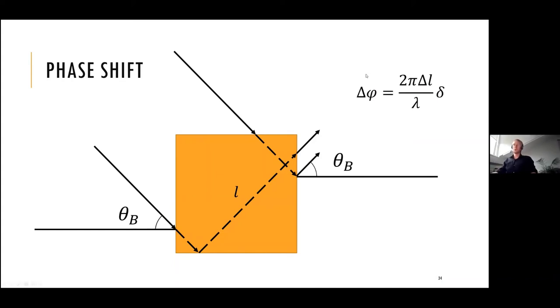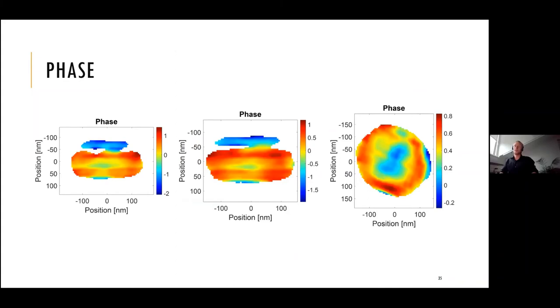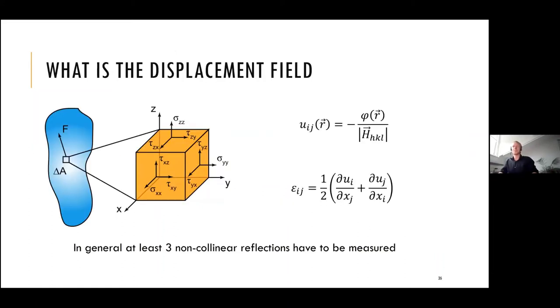And this is important to correct, and that can be easily done since you know the morphology of your object. You just have to take care of that and compensate. Otherwise, the phase information will give false information on the strain or displacement fields. So after all the corrections, we have our nice phase reconstruction. These are the central slices of the gold nanoparticle. And now we can go towards the quantitative results.